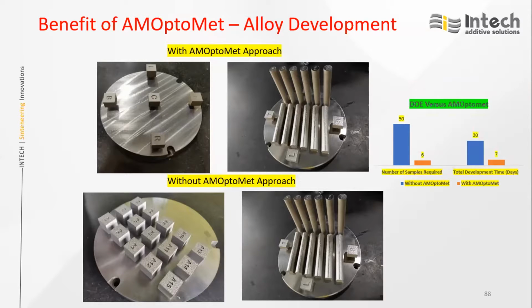In the right side graph you can see the number of samples required. With Optomet, with less than 10 samples we can get the good parameter, whereas without Optomet we need to print so many test blocks - the time for developing the process parameter without Optomet is 30 days. With the normal DOE approach versus Optomet, we were able to develop the process parameters within a week's time.